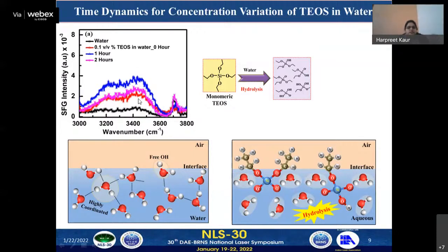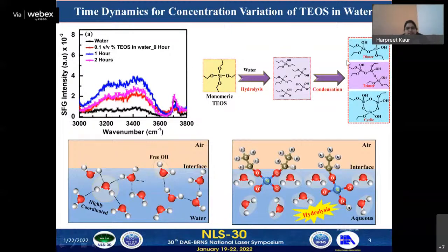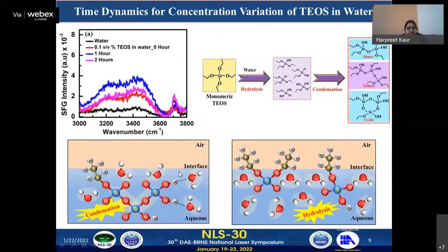And further, with time, we have found this intensity enhancement is decreased, which is possibly due to the decrease in the number of these negatively charged moieties, which confirms the condensation at the air-aqueous interface, due to which this water molecules ordering is again there. And further, with time we found this decrease is continuous, so the condensation process continues with time.